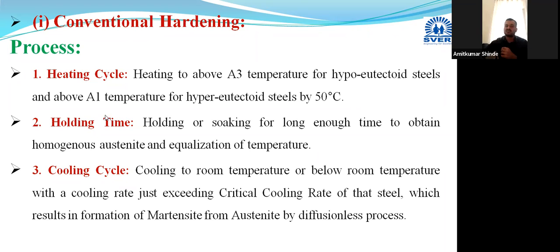And what is the purpose behind providing this holding time? The purpose of providing the holding time is to get the equal temperature throughout the cross sectional area of that component. Means the temperature should be the same on the surface of that component, and at the center of the component temperature should be the same. It should be equal. That is termed as equalization of the temperature. And another aim is to get the homogeneous austenite. Throughout that component at that higher temperature range, only austenite phase will be there. To get that homogeneous austenite phase, we are providing this holding time.